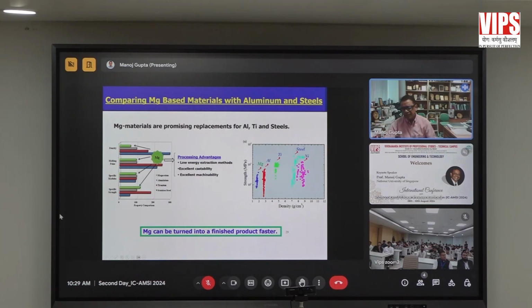Now, if you look at the graph on your right hand side, you see the y-axis is strength, the x-axis is density, and the strength spectrum of magnesium is half that of aluminum. It overlaps with titanium, steel, and nickel. So that means we can replace aluminum, titanium, steel, and nickel with magnesium when the design is a strength-based design. And to expand the use of magnesium, the spectrum of the strength has to increase so that it can be used in more and more applications.